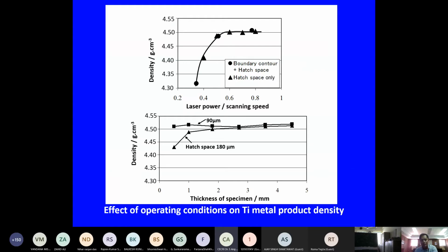so that we can obtain a component of density close to the theoretical density. And this is another fundamental study where we look at the laser power to scan speed ratio, and you can see the density of titanium powder is 4.5. At a certain laser power to scanning speed ratio, you are able to develop a component close to the theoretical density. And also the hatch space: what is the distance between the two laser beams so that I can have density close to theoretical density. From our experiment, we found that with 90 micron or overlapping scanning, we can obtain the density of our titanium component close to the theoretical density.